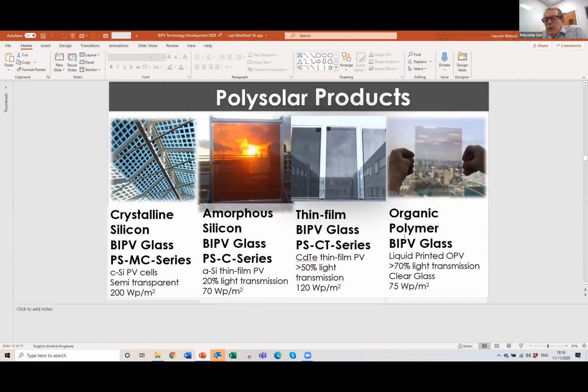More recently we developed products in the cadmium telluride sector. And this is a slightly different technology in the sense that the active material we put on and then we take off with a laser in order to pattern it to let light through, and therefore we can vary that transparency depending on what you want. Again, the efficiency is about twice what it is for amorphous silicon, but still it's about half of what it is for crystalline silicon, where we also produce crystalline silicon semi-transparent cells where you've got crystalline cells embedded in glass and the light is allowed through around that, but it isn't actually a see-through system.